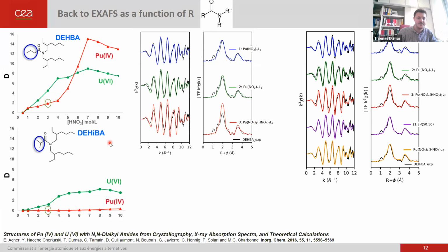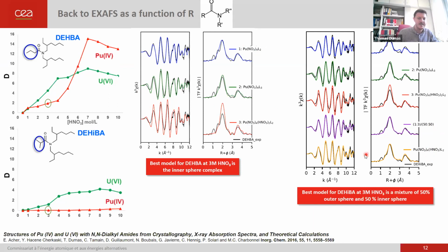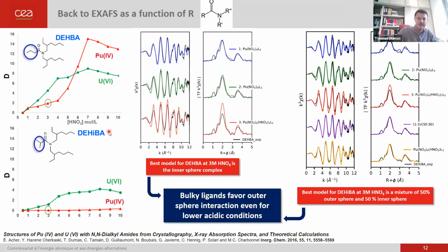And now if you look at the branched alkyl chain monoamide, what you will observe is that over all the spectra we tried, we have 2 kind of positive response from this data. If you mix up, in fact, this inner shell with this outer shell complexes, it works pretty well too. Or if you are going to work with a pentanitrate system, which is in terms of EXAFS, overall equivalent. Okay, so as I said, the best model is inner sphere complex for this one, and for low acidity, the best model for this one is a mix of inner sphere and outer sphere.